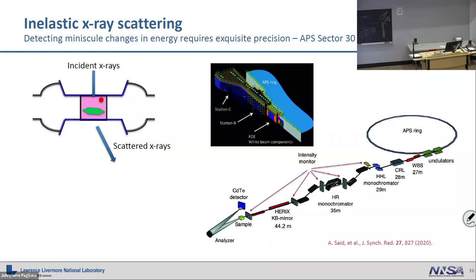You have to have a lot of stuff going on with your sample. You got to make sure you have a single crystal. You got to understand how your single crystal is oriented. You got to put it in a DAC in an oriented way so that, let's say, the C-axis is up. Now you also need to know which direction it's going in the other planes. So you need some sort of diffraction measurement to figure out the rotation inside the DAC.